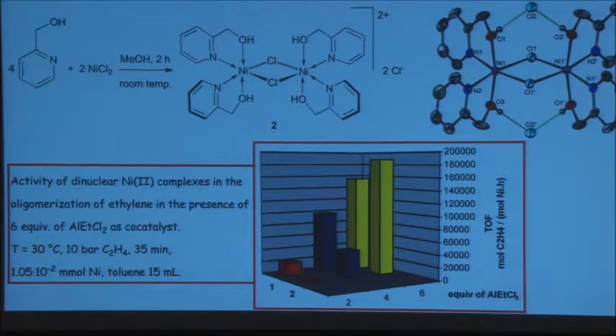But in contrast to many people who want to use a very large excess of co-catalyst, either chlorethyl aluminum or methylaluminoxane, the famous MAO, we use sometimes 500 equivalents, 1,000 equivalents of co-catalyst. The advantage is that you scavenge all the traces of impurity because the co-catalyst is hydrolyzed. So that's a way to dry your medium.